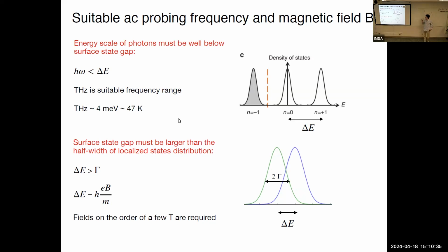That's very important. So probing frequency h times omega should be less or much less than this spacing in between Landau levels. And in real materials, this already puts you in a frequency range which is almost 1,000 times smaller than the optical frequency. So 1 terahertz is basically, its wavelength is basically 300 microns, 0.3 millimeters. So it's 1,000 times longer than visible light. Which means that you cannot observe this effect with visible light.